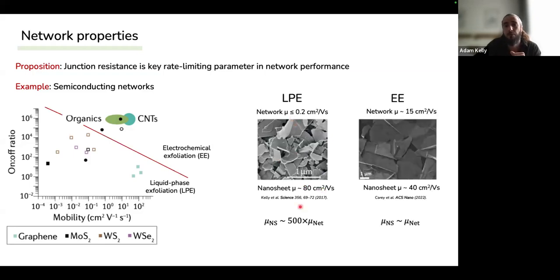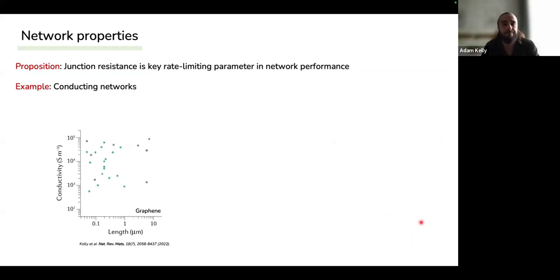When we look at an electrochemically exfoliated network, the SEM alone tells you these sit very nicely on top of each other. The junctions are very obvious. And not only that, but the junction overlap areas are huge as well. So this is good for facilitating charge transfer between your sheets. For networks like this, what we find is that the mobility of the nanosheet is on the same order of magnitude approximately as the mobility of the network.